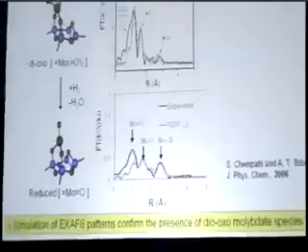And if you do the same exercise for the mono-oxo structure, you completely miss the boat. You get one peak that's in the right position, more or less, but the intensity is completely wrong, and you don't capture the intensity here at the higher distances.